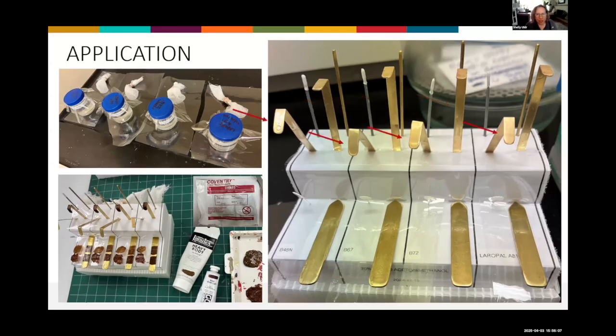Then a second bent strap that I dipped twice and then inserted into the foam at an angle to see how it would pool at the tip of the mount. And then a wider strap with the mixture applied in a fairly thick, sloppy coat to see how brush strokes would level and bubble. I basically did their worst, kind of. And finally, a Mylar strip to really test the flexibility and cracking and sheen and transparency and all that.